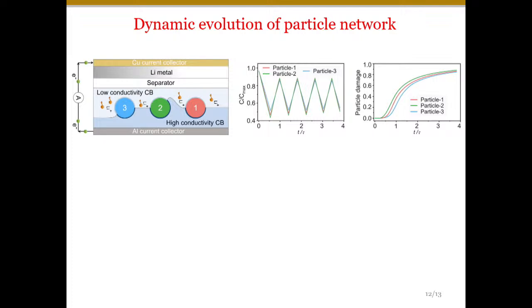So this is just a very simple 3-particle model. Particles have the same morphology, isotropic chemical and mechanical properties, but the only difference is the surface area. The reaction surface area is very different in all 3 due to the amount of high conductivity carbon binder.